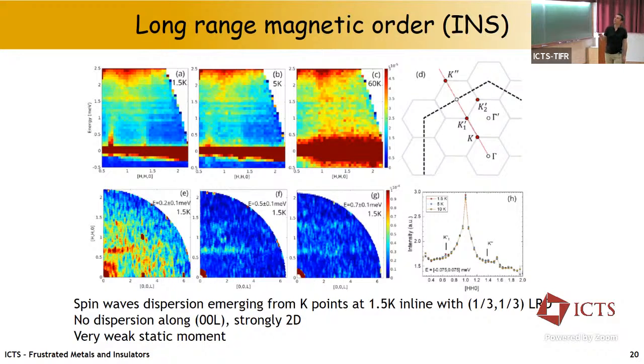So this is the dynamical structure factor at 60K, 5K, 1.5K, and at low temperature you see clearly emerging what is identified as a spin wave, which are at the K points, so which are compatible with, here it's written, 1/3 order that is proposed theoretically. Interestingly, if you look at the dispersion along C in the 0,0,L direction, it doesn't disperse at all. Actually, there are flat rods of intensity, so there are hardly any correlations from plane to plane.